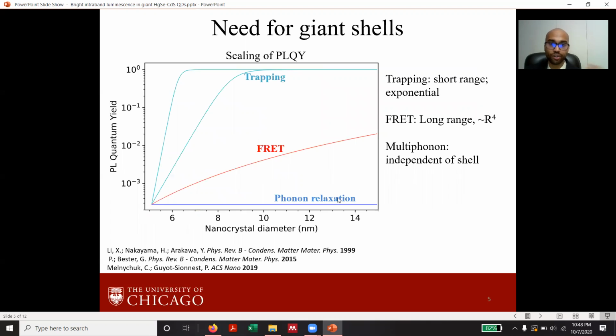Apart from multiphonon relaxation, another possibility is trapping, which is the major mechanism in the wide gap semiconductors. If trapping is a major mechanism, we would expect an exponential dependence of the quantum yield on the nanocrystal diameter. Using two limiting values for this exponential length scale, we have plotted a rough scaling of the quantum yield versus the nanocrystal diameter for a core shell nanocrystal.